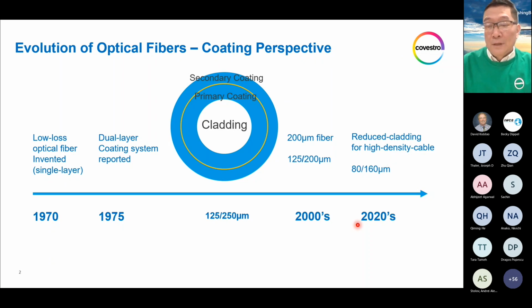So in very recent years, around 2020, which is the last 5 years or so, even another configuration was proposed, and certain corporations were able to produce commercial volume of something called 160 micron fibers, which means the glass cladding is reduced from 125 to 80 micron, and the overall coated optical fiber is only 160 micron. So you can imagine, with the given space in the cable, we can fit more such dramatically reduced size fibers into the same cable space.